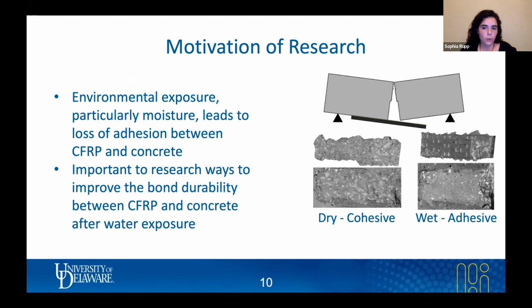Despite all of the great properties of CFRP that I previously mentioned, there has been prior research done that has shown when CFRP is exposed to water in the field, it will lose adhesion between the CFRP and the concrete. When a strengthened member is subject to flexure and it's dry, we typically will observe a cohesive debonding failure, which indicates that there is good bonding between the CFRP and concrete. However, when it's wet, we will experience an adhesive debonding failure, which indicates that there's poor bonding between the CFRP and concrete, and the CFRP essentially peels away from the concrete.